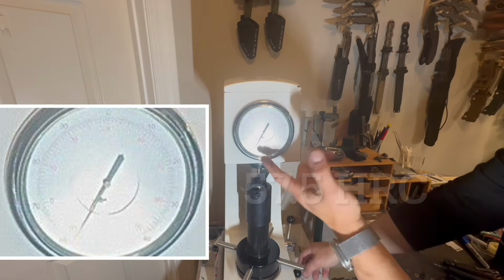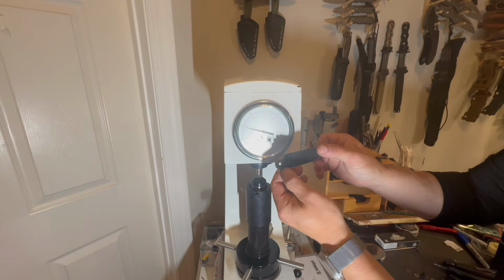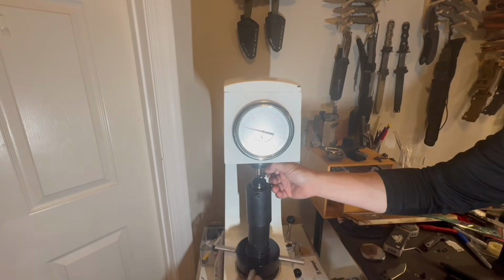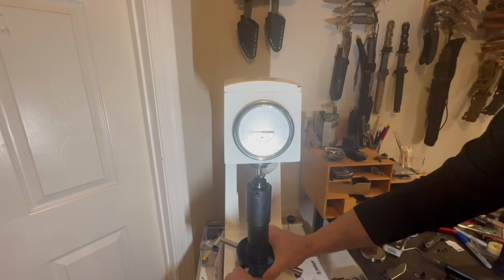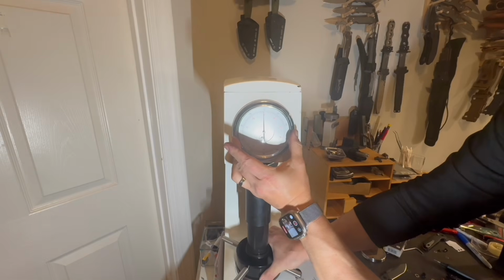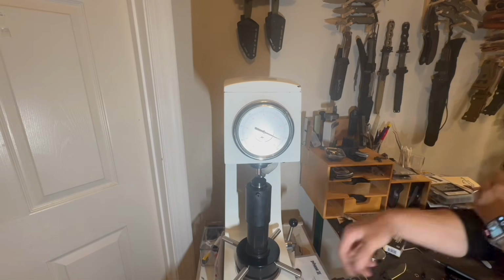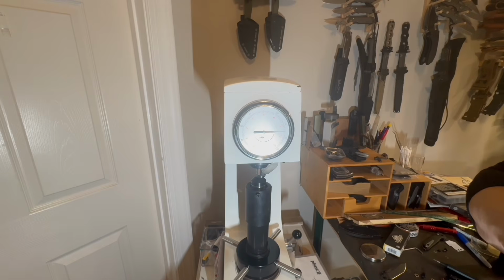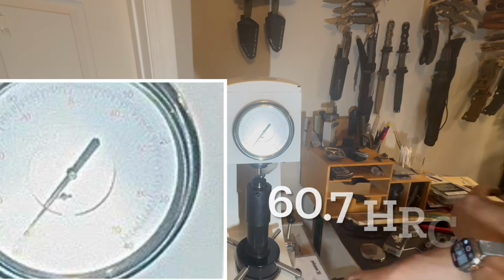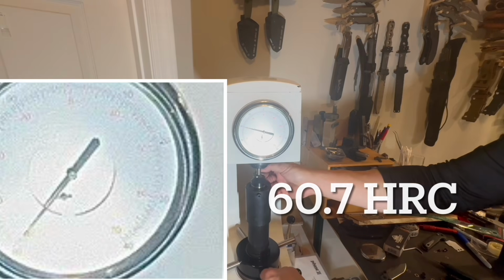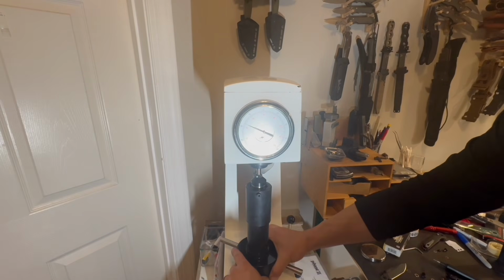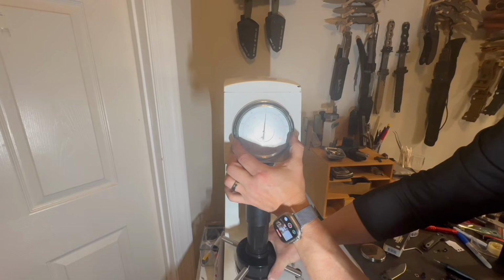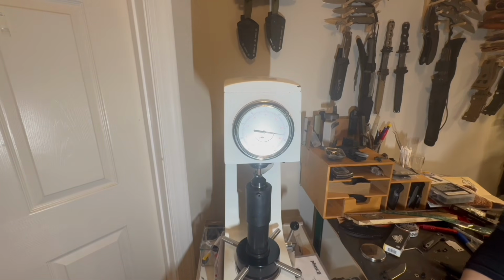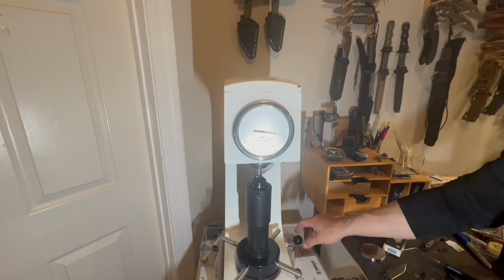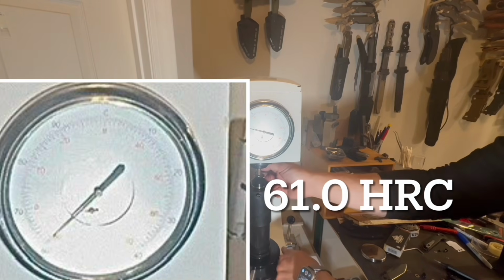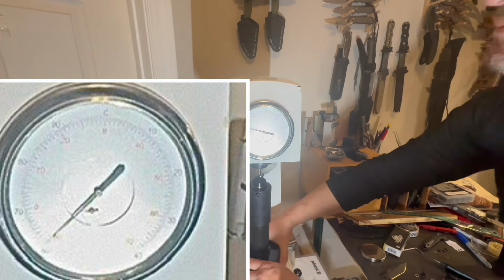57.5 HRC. The majority of basic stainless steels temper at a much lower temperature than some of the tool steel varieties. By the way, I switched to the Iridium's blade here, which is made of somewhat corrosive yet uncoated D2. Almost every manufacturer does this stupid crap, and I don't understand why. If the design aesthetics calls for a coated blade, 60.7 HRC, just make it out of D2 or 3V, and then the coating is justified. And because they temper at much higher temperatures, the coating will not affect the final hardness. So no pre-planning is required.